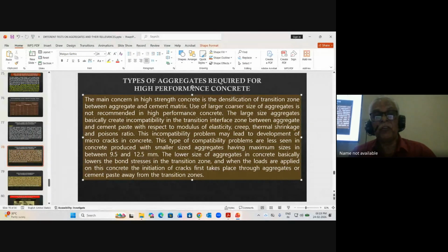Incompatibility may lead to development of micro cracks in concrete. So the higher the size of aggregate, more so in high strength concrete and ultra high strength concrete - we never use a very large, say 20 mm size aggregate.